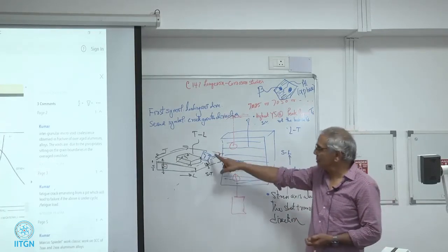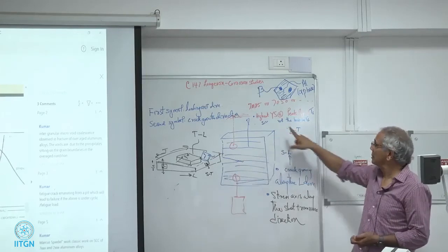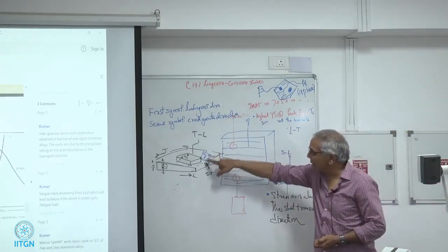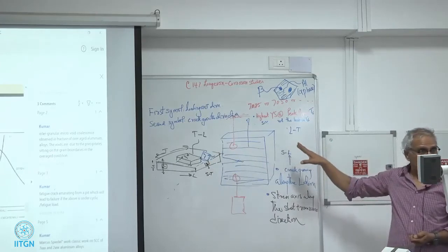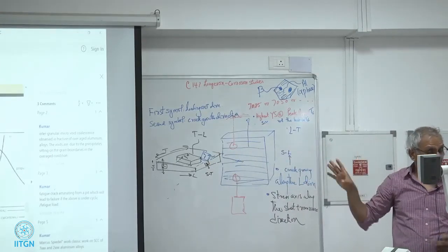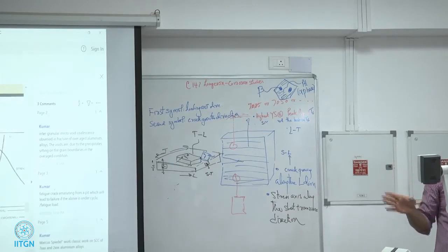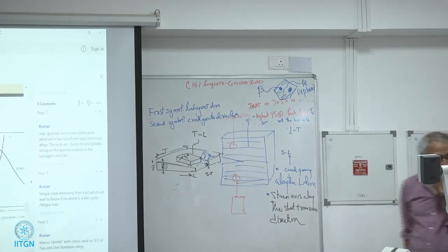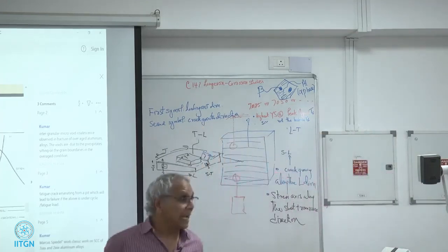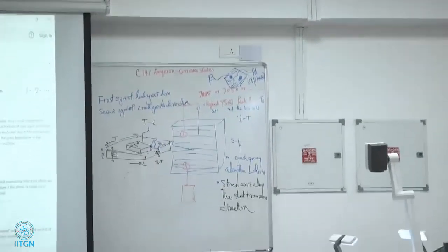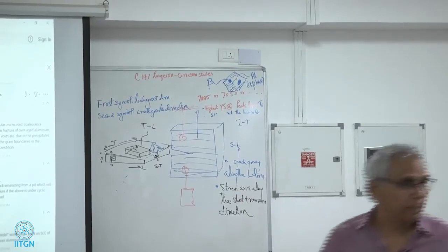So my first symbol is the loading axis, and my second symbol is the direction in which the crack is growing. This is what we follow for the fracture mechanics samples. If you don't give this, then we're in trouble. L is rolling direction. S is the short transverse. T is the long transverse. So this is the designation that we follow. It's not the best drawing in the world, but I'm hoping you get that picture.